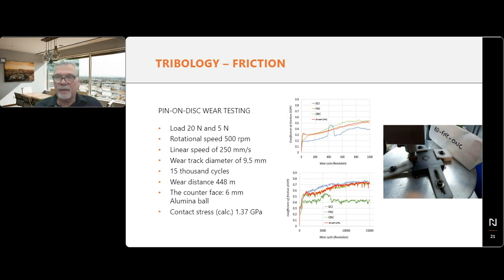Nitrocarburized surfaces seem to offer a better grip, even despite post-oxidation, which in theory at least should lower the coefficient of friction. One last note on that subject is that typically trials are done at higher temperature. Here, all the trials that we had access to were done at ambient temperature.